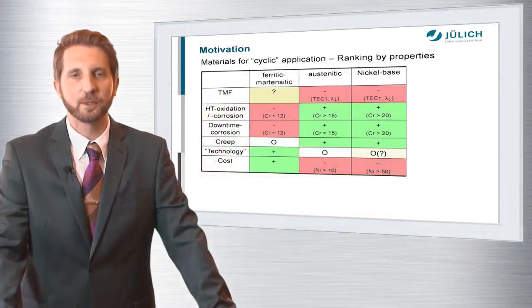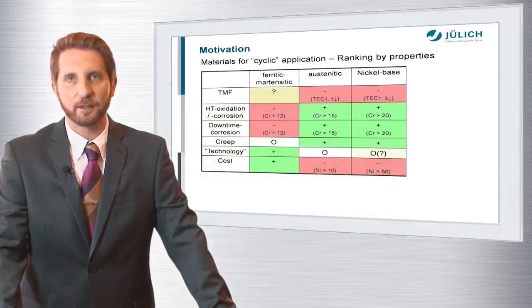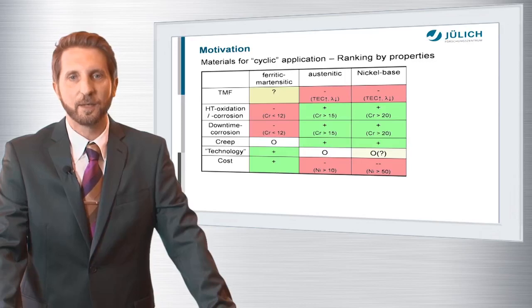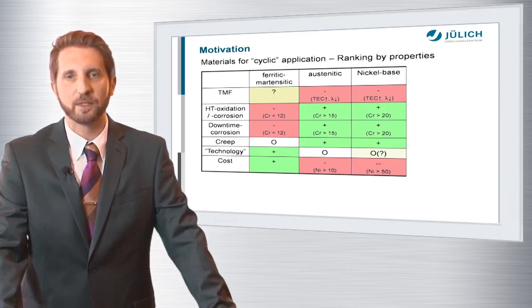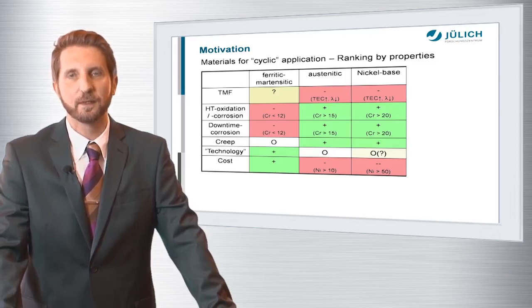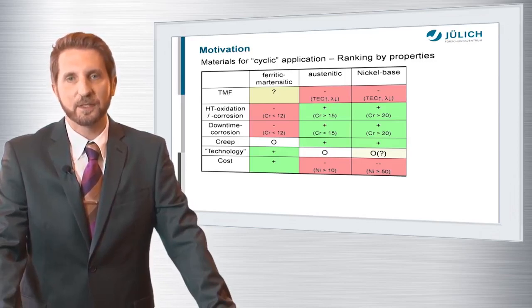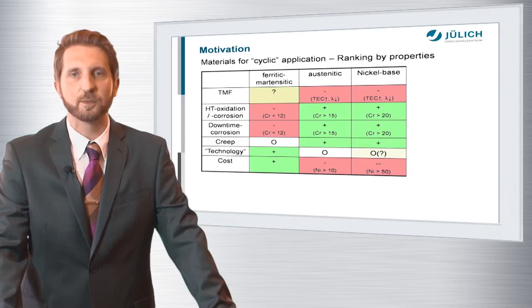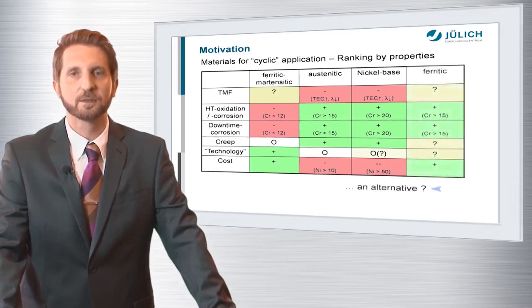But for sure, what is a problem today and will remain a problem is the higher cost that is implied by the use of austenitic steels and especially high-performance nickel-based alloys, because the nickel contents, especially in case of the nickel-based alloys, are higher than 50%, which leads to exaggerating costs.